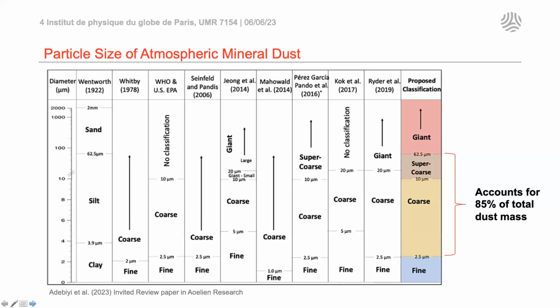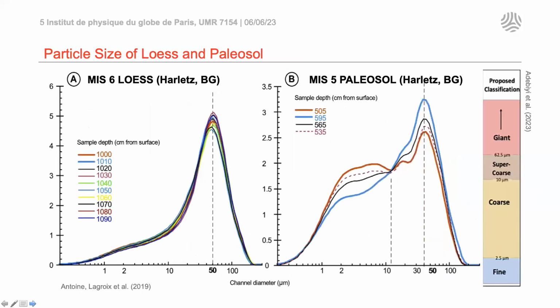So if we look at this classification and compare it with a very typical grain size distribution of loess on the left-hand side from the penultimate glaciation and a paleosol of stage 5, we can see that we have a mean distribution of the loess that's 50 microns, so we're in the upper range of the super coarse based on their classification. But there's also a continuum of all the grain sizes all the way to the finest in the loess.